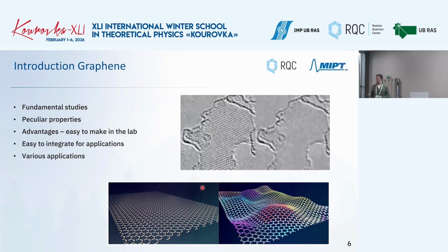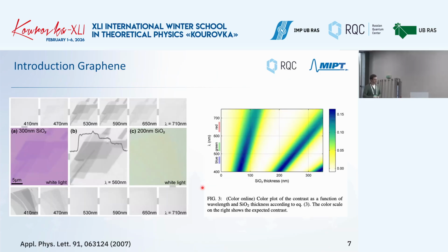And basically you, I suppose, all know that you can have this Scotch tape technique, and then you can, with the Scotch, obtain monolayer graphene, let's say quantum material. Yeah, and why is it so? Because, for example, it was described in 2007 that simply by looking at the optical microscopic contrast, you can see these flakes. So sometimes you cannot see it, but sometimes you can easily see something.